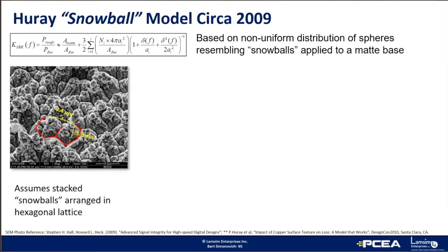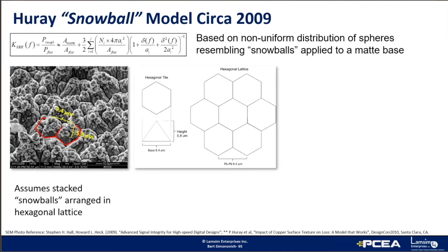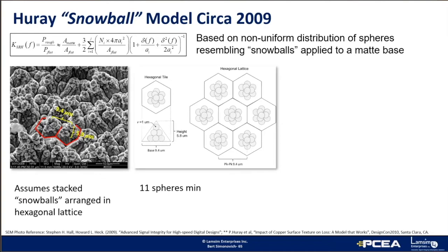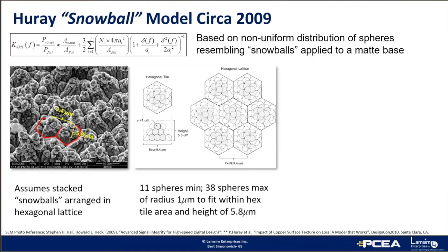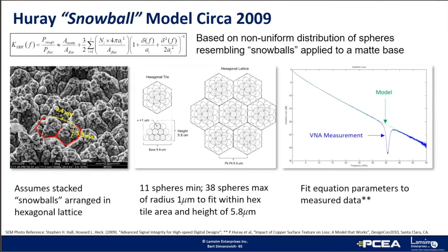The model relied on SEM photos of the roughness profile, then assumed stacked snowballs are arranged in a hexagonal lattice arrangement. You would then estimate the peak-to-peak separation, stack height, and sphere radius. Then you'd create a lattice picture and figure out how many spheres to be stacked on a hexagonal tile base. In this case, with 1 micron sphere radius and peak-to-peak separation of 9.4 microns, we can fit a minimum of 11 spheres, up to a maximum of 38 spheres. Then you'd play with the number of spheres until you fit the measurement. And as you can see, the model fit very well. But the main issue with the Huray model is that it's cumbersome to get the right parameters without a lot of trial and error in tuning to a measured test sample.